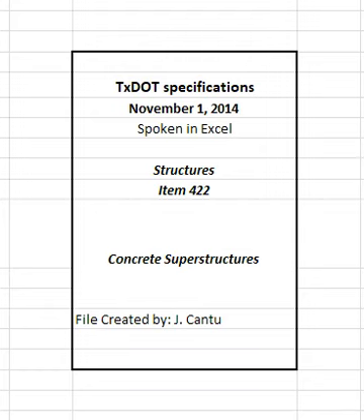Do not place concrete in contact with any material coated with frost or with a temperature of 32 degrees Fahrenheit or lower. Do not place concrete when the ambient temperature in the shade is below 40 degrees Fahrenheit and falling unless approved. Place concrete when the ambient temperature in the shade is at least 35 degrees Fahrenheit and rising or above 40 degrees Fahrenheit. Provide and install recording thermometers, maturity meters, or other suitable temperature measuring devices to verify all concrete is effectively protected.